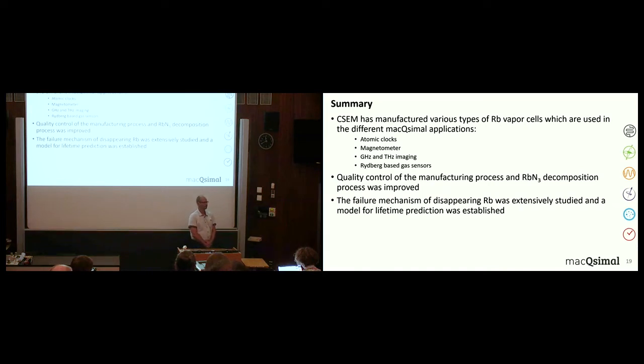Then we have a question by Ilya again. Was there an option tested with anti-relaxation coatings as, for example, ODTS? No, this was not done. We have always to be compatible with our fabrication process, which involves anodic bonding, and this has to be done at a higher temperature, clearly above 300 degrees, and all relaxation coatings that cannot withstand this temperature, they are out.